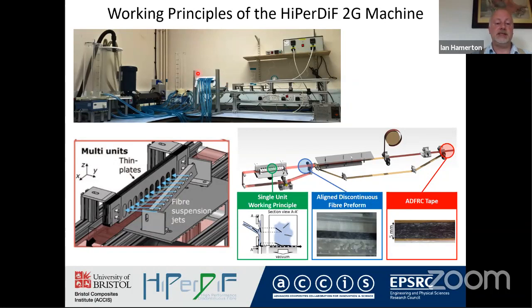of magic happens here. This is the distribution head in which the fibers in suspension are actually projected, they're jetted through these apertures. And if we look downwards on this, between the plates, what we have here are a series of plates which are finely divided. So the discontinuous fibers are projected and they strike the back plate. And as the fibers strike the back plate, they transfer the momentum, they fall, they're sucked to the bottom of the plate by a vacuum.